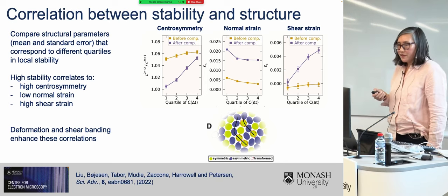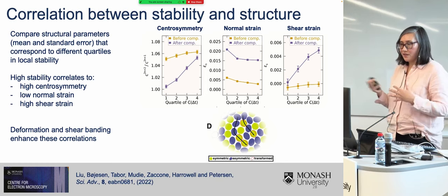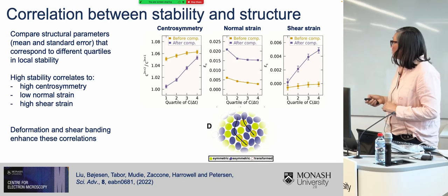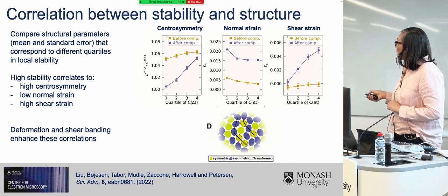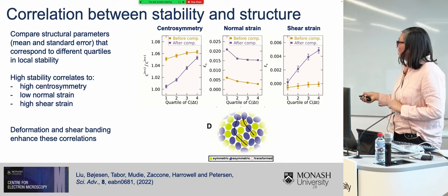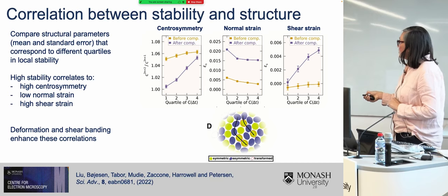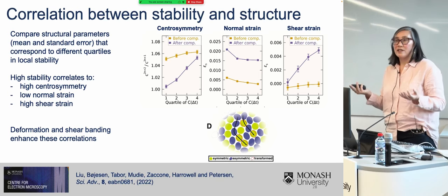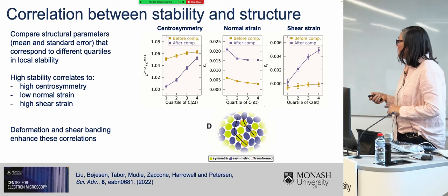So you can also mine these maps a little bit more to try to understand these different correlations between the parameters. So here I've plotted out the mean and standard error of the structural parameters, so the centrosymmetry, normal and shear strain, as a function of the quartile in the local stability. So from these plots you can see that high stability, so the fourth quartile in stability, really does strongly correlate to high centrosymmetry, low normal strain and high shear strain. And that these trends are actually very much exaggerated once you've deformed the material.